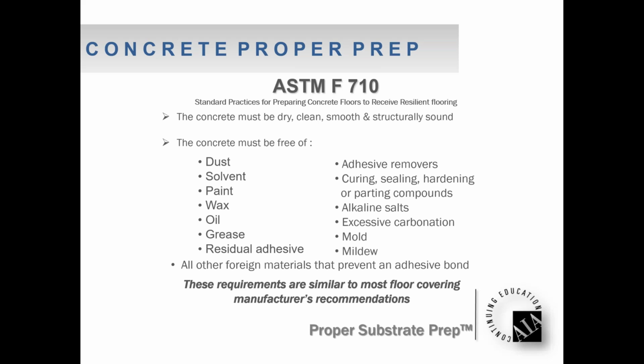The bottom line with solvents, and here's the difficult thing. The adhesive remover, the solvent, it doesn't know the difference between the existing adhesive and the new adhesive that's going to be installed. So it does a great job dissolving the glue on the floor. You end up removing 95% of it. And what's left is a broken down residue of glue and solvent that's left in the pores of the concrete that can migrate into the pores and then eventually come back out. It can affect your new adhesive, it can affect your patch or leveling product. Things start to fail, okay?